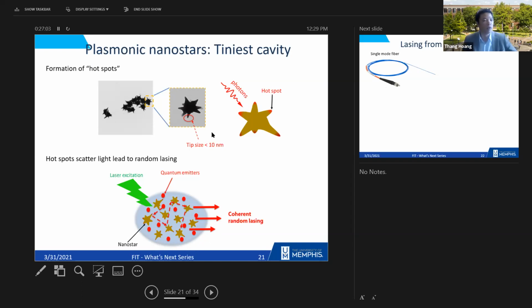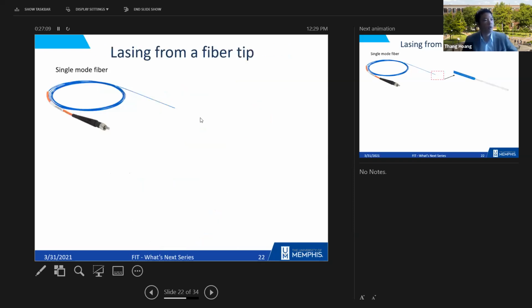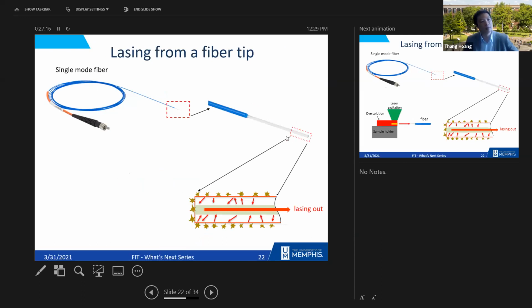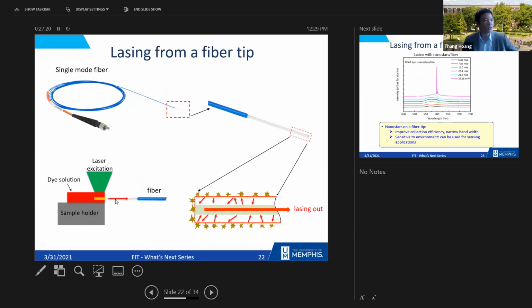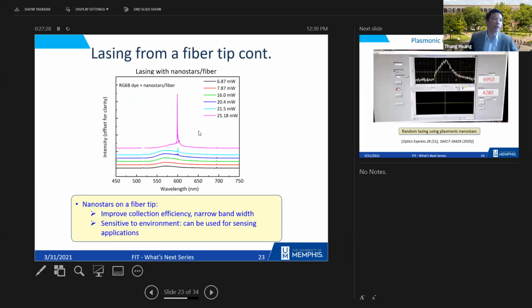So this is a new phenomenon, and that's exactly what we did. And we go beyond that. We take a bare optical fiber and coat it with a nanostar, then put that in a dye solution, and we can excite that tip with a laser and get lasing out of it. So basically, we demonstrate lasing from the tip of an optical fiber.